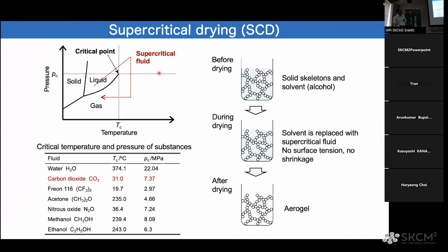Supercritical drying is a drying process using supercritical fluid. And as you know, over the critical point, higher pressure, higher temperature, there's a region of supercritical state. And at first, the liquid in the gel can go through the supercritical fluidic state, which doesn't have surface tension. Then you can avoid the shrinkage and cracking of the gel, okay? So after the supercritical state, you can decrease the pressure and temperature to make the fluid into gas. So this is a drying process.